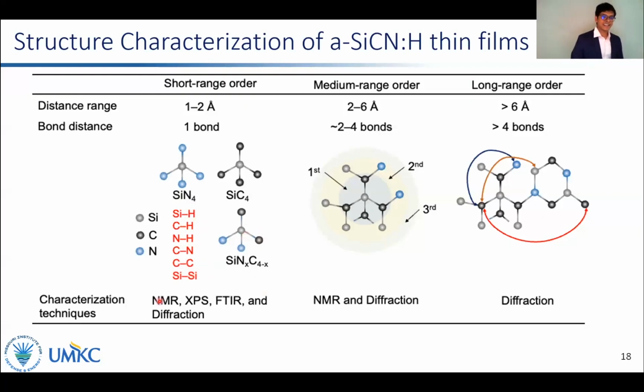Structure at this scale can be elucidated by NMR, XPS, FTIR, and diffraction. On the medium range order scale, approximately 2 to 6 angstroms, corresponding to 2 or 3 coordination spheres around the local structure, structure can be elucidated by NMR and diffraction. Long range order, greater than 6 angstroms correlations, can be elucidated by diffraction studies.